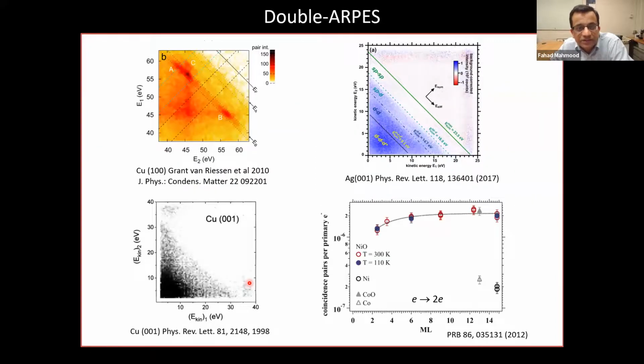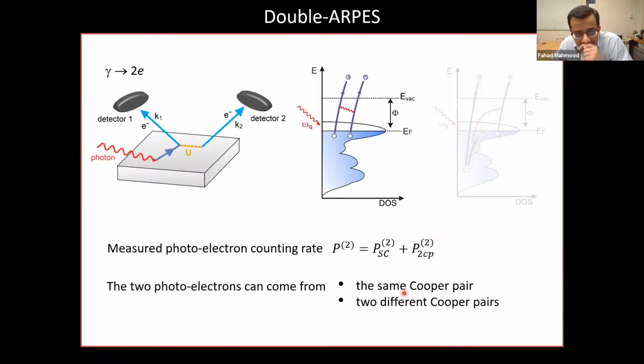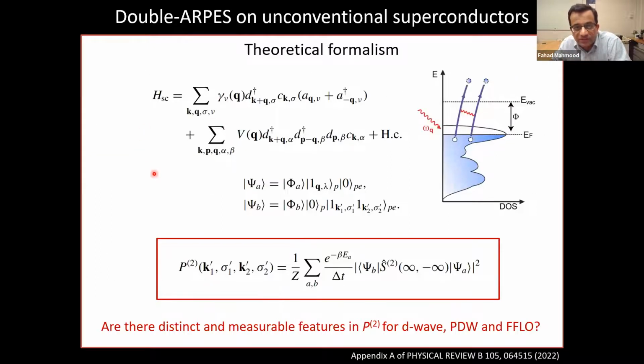So we're not the first ones to think of this. This has a long history. There's also some very nice theoretical work done on this type of technique, or at least multi-electron techniques. And it's been shown, for example, for the case of nickel oxide, that this two-particle counting rate, if we do photon in, 2 electrons out, or electron in, 2 electrons out, is orders of magnitude higher in the case of a strongly correlated material like nickel oxide compared to non-correlated materials, right? So we immediately know that this is a very good probe of correlations. Okay? So we want to do this as a function of energy and momentum, right? Okay. So just to guide you over the theoretical details very briefly, I won't go into much detail here, but what our paper is doing is essentially calculating this two-particle counting rate for photoemission, and it is based on this Hamiltonian for photoemission.